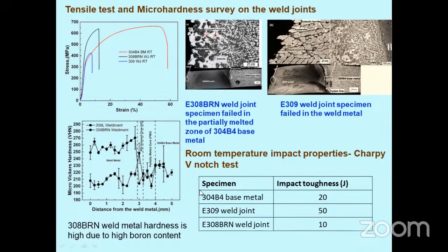So now coming to impact toughness, we see that this boron added weld joint has a very low impact toughness because it is fully eutectic borides, very brittle in nature, and so impact toughness is low. The base metal has around 20 joules impact toughness at room temperature, whereas in case of 309 electrode, which is boron free, and the notch is put at the center, we have a higher impact toughness value. So this E309 electrode can be used where impact toughness requirement is mandatory for welding this borated stainless steel.